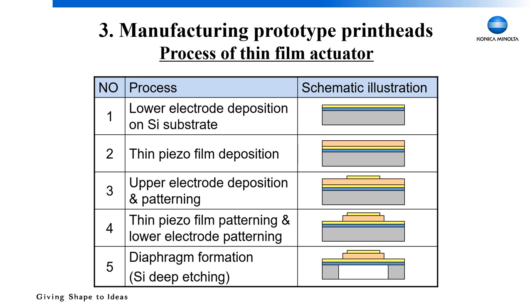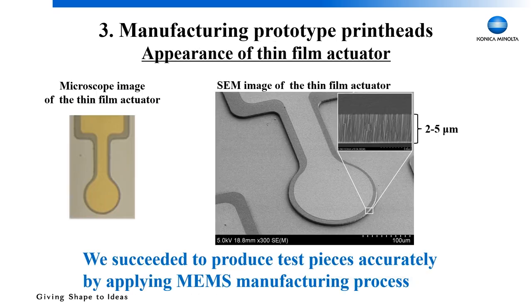This is the appearance of the thin film actuator of our prototype printhead. This is a microscopic image and this is an SEM image. The upper square part shows the bonding pad for testing and the lower circular part is the actuator part. The silicon substrate opposite to this circular part was removed.